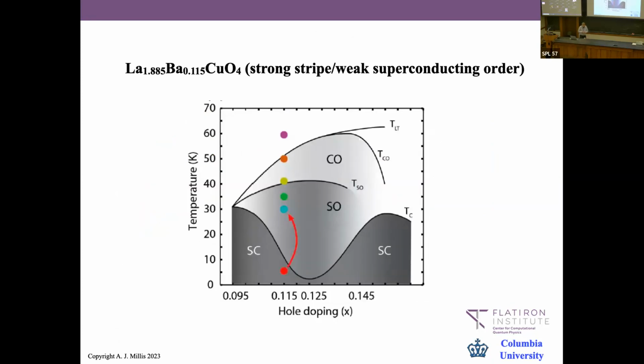Here's another example, which I'll come back to. This is a particular material in the high transition temperature cuprate class of superconductors. It's peculiar because it has a superconducting phase with a transition temperature that depends on carrier concentration, and the superconducting transition temperature has a pronounced minimum at a carrier concentration of 1/8 carrier per unit cell. This carrier concentration is associated with a charge and spin order—basically a competing order.